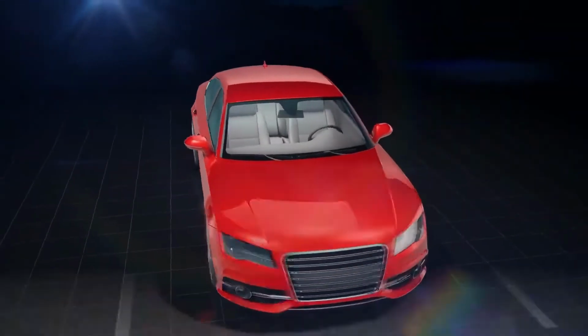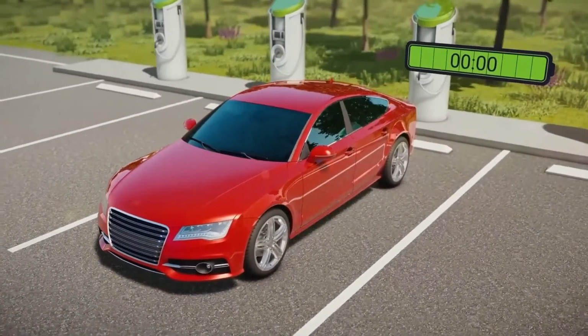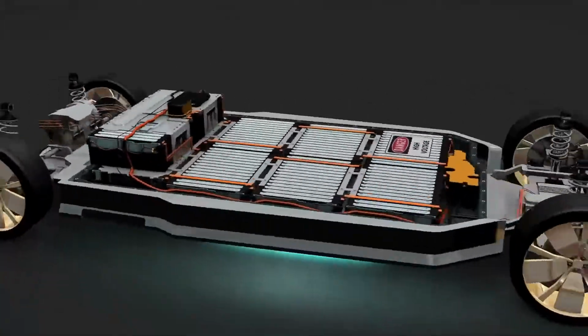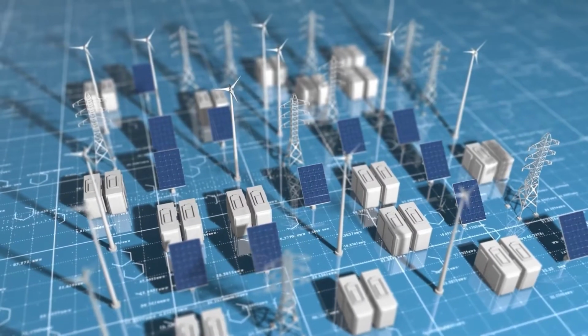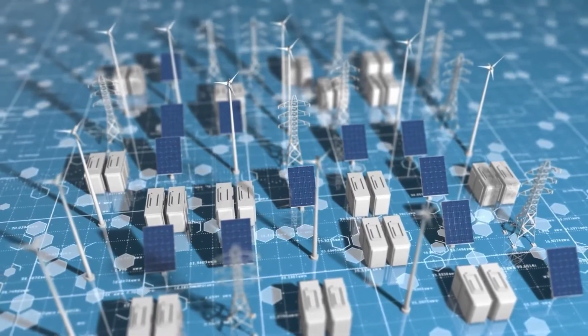The company claims that its new battery cell can maintain an optimum performance even after 1,000 cycles and 80% capacity, at the point which rival lithium-ion fast-charging technology cells start to rapidly deteriorate in performance. It further claims that even after 1,700 cycles, which is long after the accepted industry norm, its battery can still maintain about 70% of their original capacity, making them effective in their second-life usage.